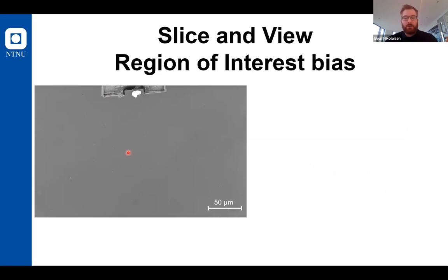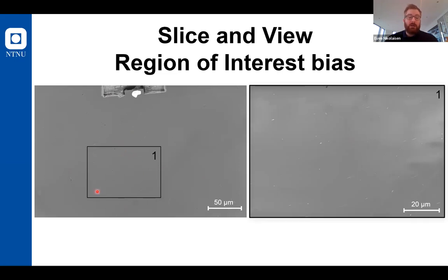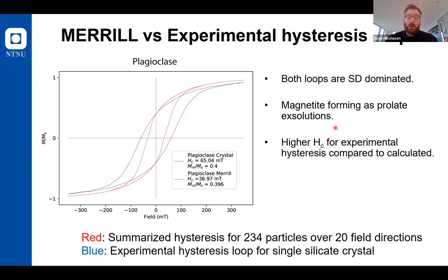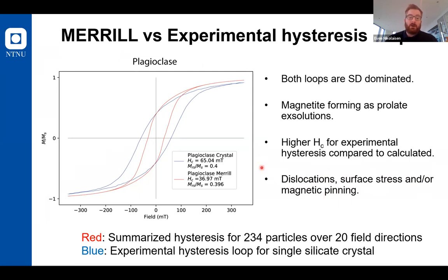The reason for this is the exact opposite of what we saw in the OPX, where the region that we can extract with slice and view is actually quite much smaller, but it does include all of the magnetic particles that would be represented. The only thing we question is whether this volume actually has an equal distribution of the single domain particles, which is questionable. Another reason for this offset could be natural features like dislocation, surface stress, and magnetic pinning, which could also produce an offset for the coercivity.